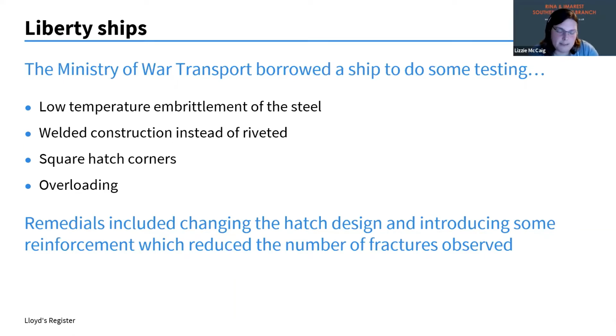Then combine that with the fact that because it was a war, the ships were often overloaded, and again they were sailing in winter, so they were subjected to storms. So all these things combined together didn't make for very good design against brittle fracture. Some of the things they did to address this was they changed the hatch design and they reinforced the ships, which did reduce the number of fractures observed.